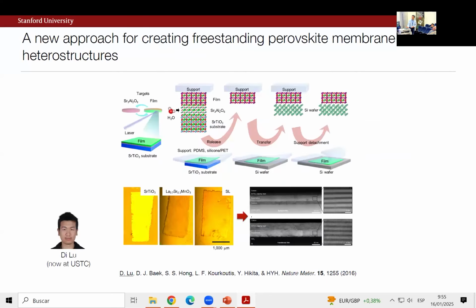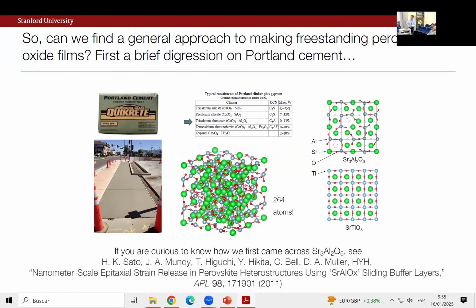In a simple-minded picture, the atomic density of this buffer layer is a little bit reduced, right? I have some vacancies inside. So it's almost like the other part that we were discussing: what is the energy cost of that dislocation core? It has to do with the Young's modulus and so on. Presumably, compared to a dense perovskite, it will be lower energy. So phenomenologically, if we're plus or minus 1% for a given soluble buffer layer, often things can work out, meaning we can have apparently clean membranes, we don't have macroscopic cracking, and limited defects. But if we go above that, many problems occur.